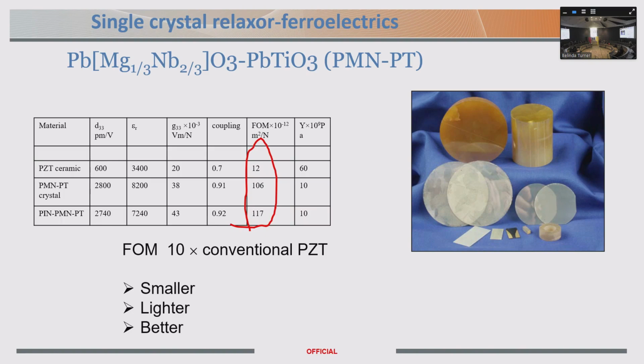But you can see that their figures of merit, in terms of the maximum energy that they can extract from the field per unit volume, is an order of magnitude higher than PZT. So what that means is that we expect to be able to make devices that are much smaller and much lighter, remembering that lead is a particularly heavy material. But that's not quite the full story. That's not quite what we mean by sensitivity.